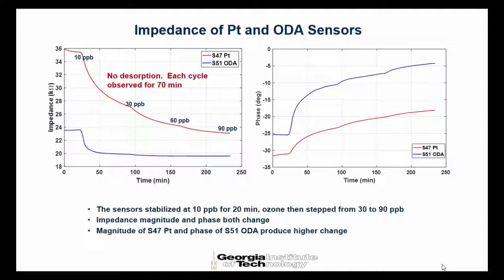Then we made 2 different sensors. One is platinum and one is ODA. Unfortunately, I don't have time to go through the details, but I just want to say that this is the impedance magnitude and this is the impedance phase. You can see that one of the sensors, the platinum, responds well in magnitude, and the other sensor, that is ODA, responds well in phase. So this is a very good input to start the experiment, right?